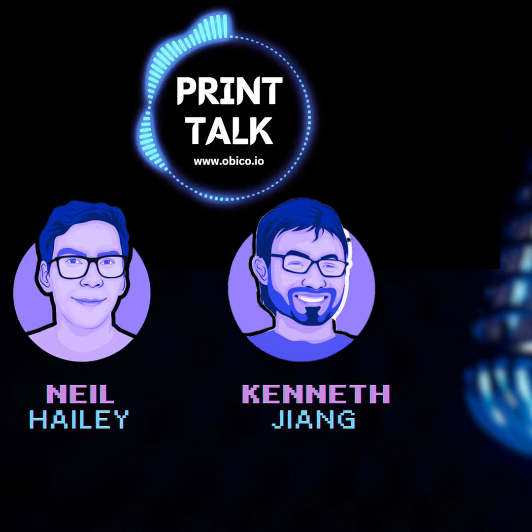Is it as easy as hitting print, or do we need to tweak things for nylon? Nylon is definitely less forgiving than PLA when it comes to print settings. You can't just slap on a standard profile and expect perfect results. All right, let's break it down. What are the key settings we need to pay attention to, and why? Temperature is always crucial, but it's even more so with nylon. Start with the manufacturer's recommended range, usually around 250 to 280 degrees for the nozzle and 70 to 90 for the bed. But don't be afraid to experiment.